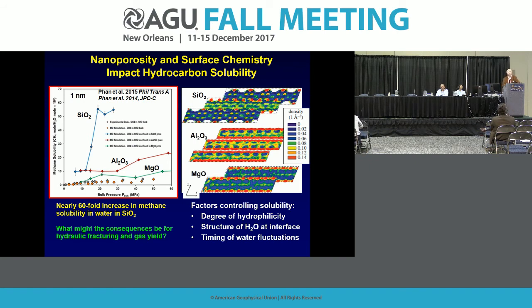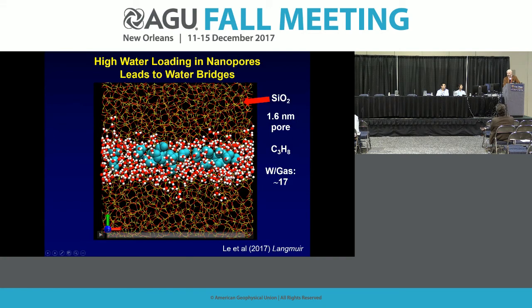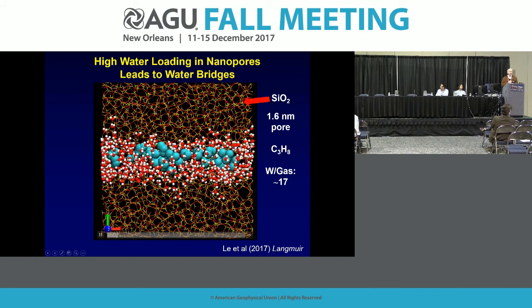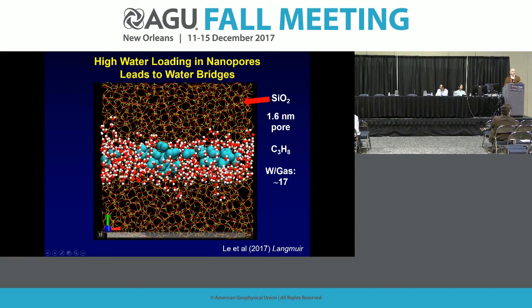So we learned a very interesting outcome here, that at this length scale, depending on that surface, we're going to have a different kind of behavior for methane in terms of solubility. It's also true for transport, which I'll get to in a minute. But here's a case of water in a silica pore. So what happens here in terms of the actual structure that's changing within this pore? It's a silica nanopore, 1.6 nanometers. Again, another simulation that we did.